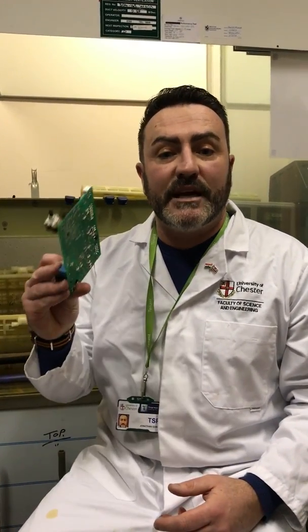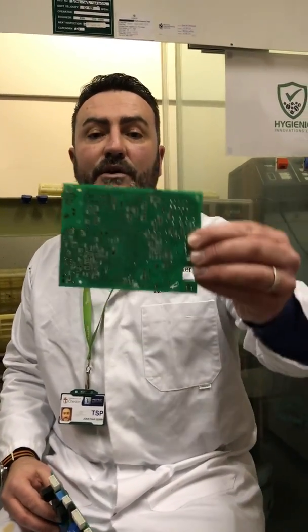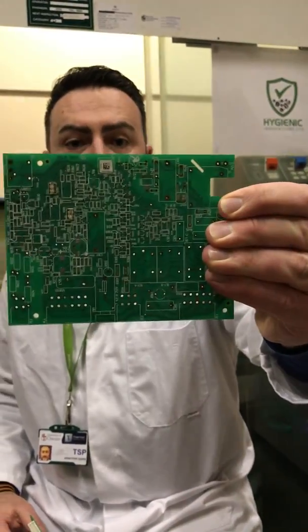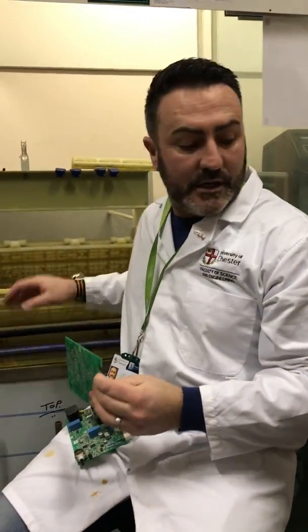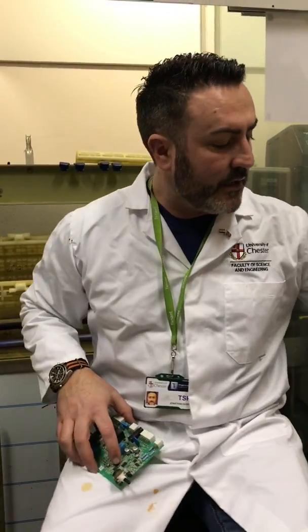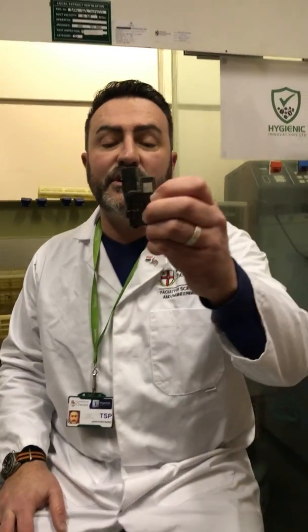If you leave the printed circuit board in the chemical formula on its own, it takes around 7 or 8 hours to dissolve the solder. Because of the ultrasonics, it takes about 20 to 30 minutes. So the main idea of this technology is we safely remove all the solder. That leaves the empty board as well as all the components inside the cage. We've removed all the components, so you can send them to whichever you want to recover more value. First of all, we'll talk about the chips. The chips contain precious metals, and they can go off on their own to recover all the precious metals.